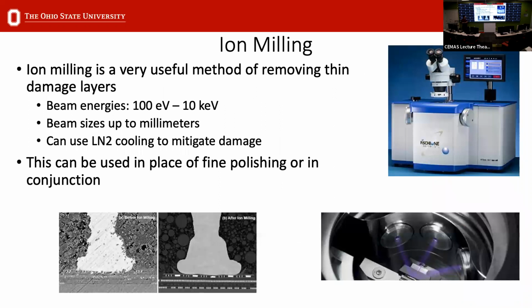So another commonly used technique is ion milling. There are various systems available that use broad beam argon ion milling to remove damaged layers. In some instances, I've talked to people who've done their sample prep completely with ion milling. It's just a matter of how much time you want to actually spend doing it. But you can typically configure an argon ion mill to mill between energies of 100 electron volts and 10 keV, and you can modify your beam diameter to be microns to millimeters in diameter. In addition, you can use liquid nitrogen cooling to mitigate damage as you remove those layers.